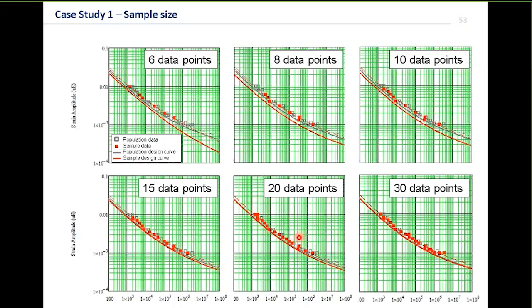By the time we get up to typically about 25 points, that's really where we get the optimum design curve for about a 97.5, 95 curve. Adding more than that isn't necessarily going to help us. If we take less than that, then we start to either get bias in the data, or we start to get a significant safety margin because of the design requirements that we're looking for.